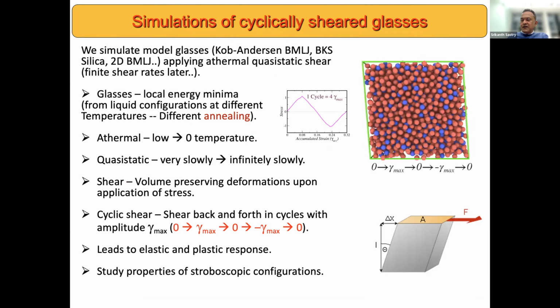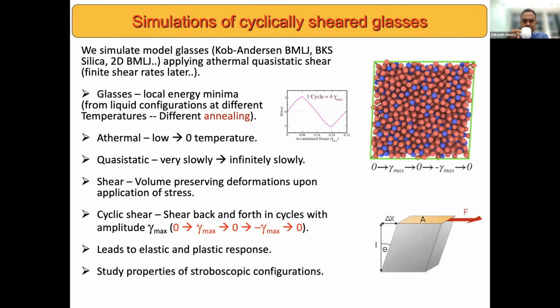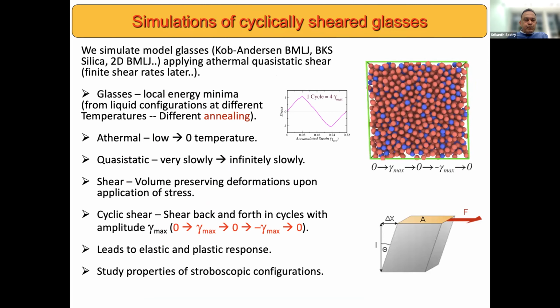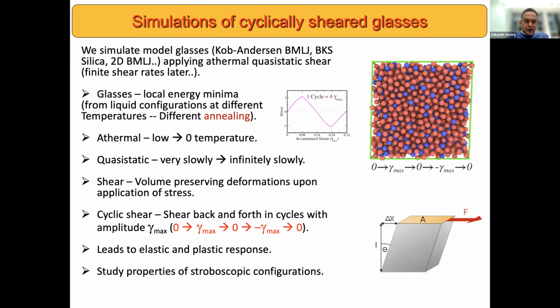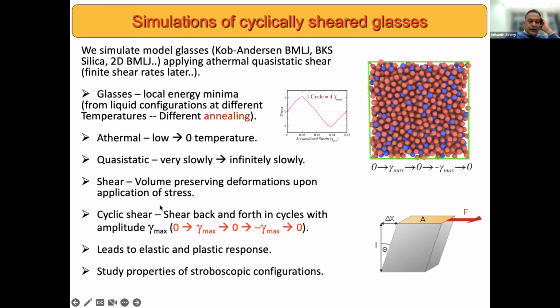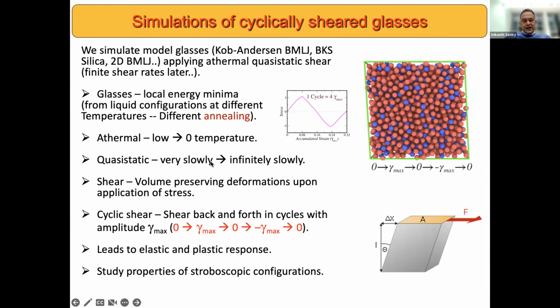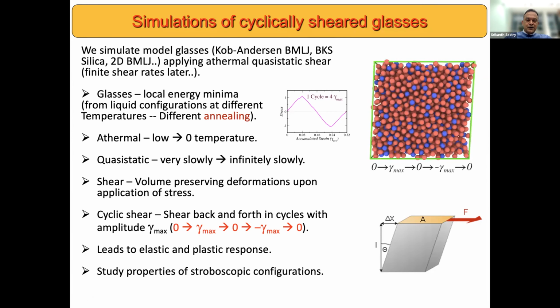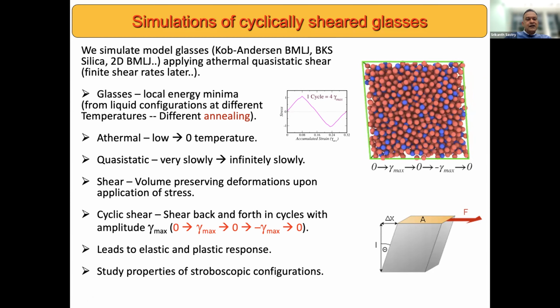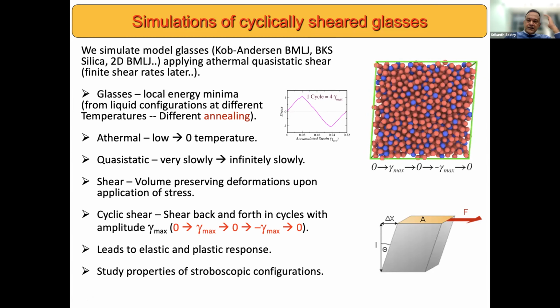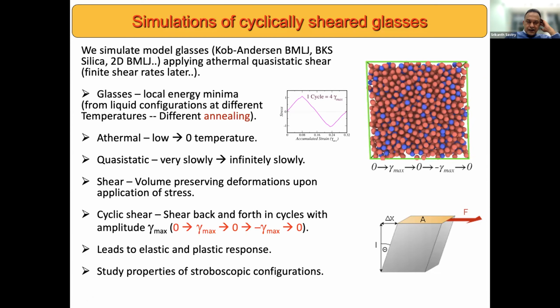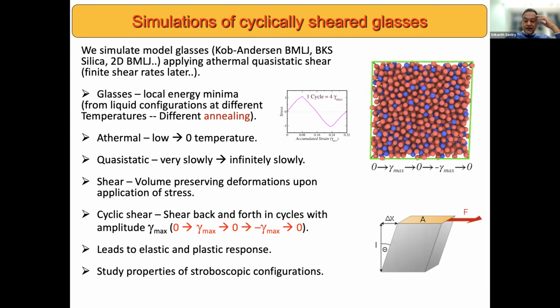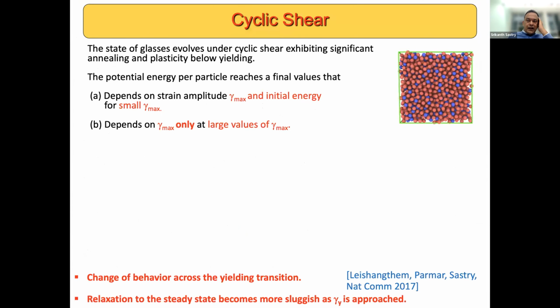Now, here is a thumbnail sketch of what we do in our simulations. We study a number of different model glasses, using the athermal quasi-static shear procedure, and the cyclic shear deformation is illustrated by this video clip, where one goes from 0 strain to a maximum strain, back to 0, and then to a maximum negative strain, and back to 0. And this cycle is repeated again and again. And one typically studies the properties of configurations at the end of each cycle. So what happens when one does this repeatedly?